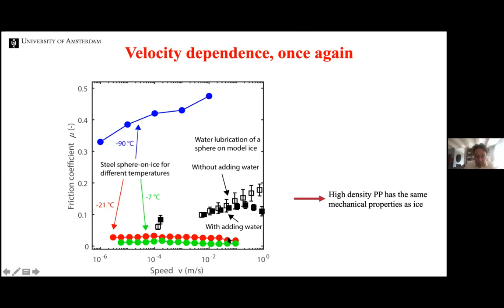There's another interesting experiment shown here for the believers in the water layer. What one can do is take a plastic surface, high density polypropylene, that has the same mechanical properties as ice, and do a dry sliding experiment and a sliding experiment lubricated with water, and you see that they actually give high friction coefficients, and that the addition of water only matters at really high velocity. So the water layer actually doesn't explain at all why